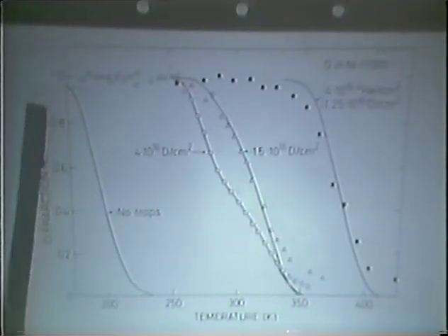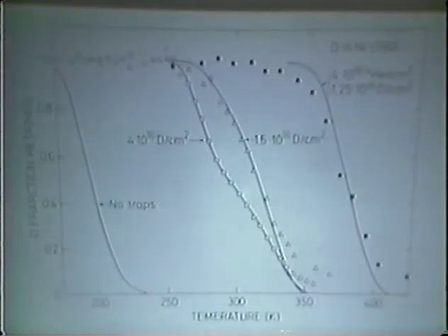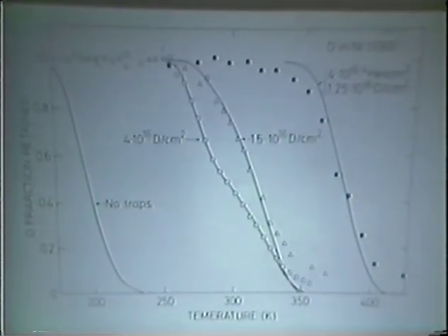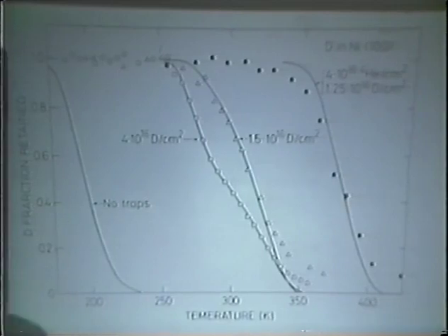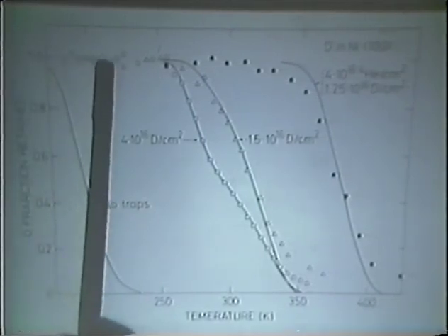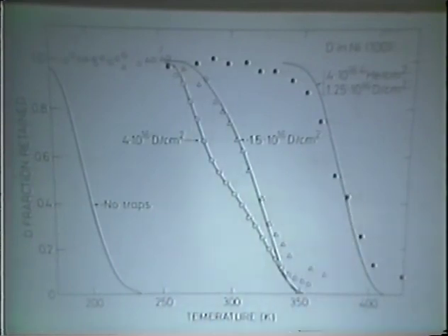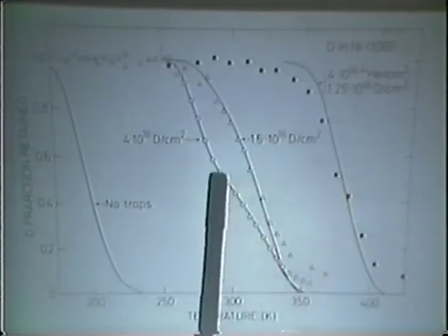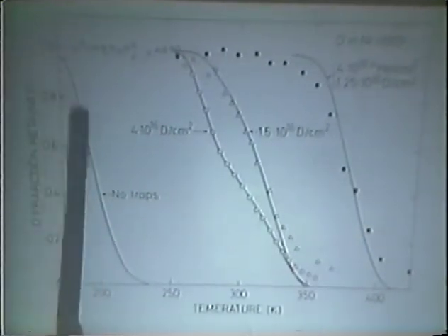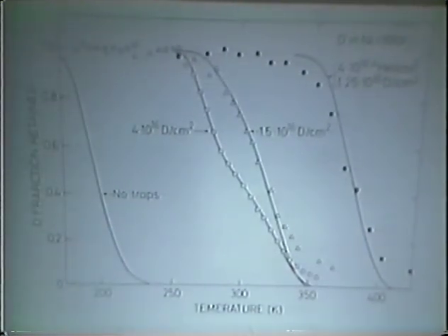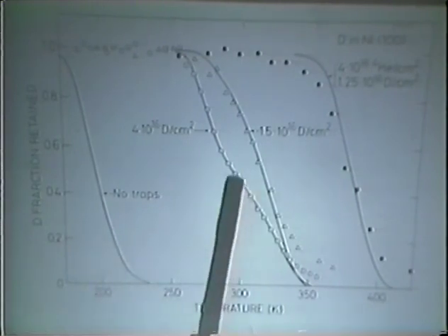Before I show you some annealing curves for deuterium, I'll show you some for nickel, because they are maybe easier to understand. So what I have plotted here is the fraction of deuterium retained in the lattice, normalized to 1. We have implanted deuterium at low temperatures. Then we anneal up the temperature with a linear ramp at a rate of the order of 1 to 2 K per minute. We then continuously probe how much hydrogen is left in there, and we get some annealing stages up here. The first thing you can see is that all these annealing stages are well above the curve calculated for the case of no traps available, where we have perfect lattice diffusion out of the crystal. So they are associated with hydrogen trapped at defect sites up here.